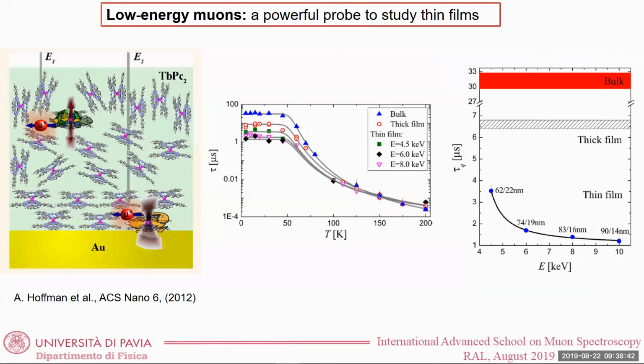Just to give you an example, this is again a molecular magnet, terbium phthalocyanine. In this study, done at LEM at PSI, we managed to learn, by studying the relaxation rate of muons implanted at different depths, in one case close to the gold substrate and in the other case far from the substrate, that the dynamics of the spins of this terbium in this organic molecule was quite different close to the surface. The dynamics was much faster, rather than, you see a turtle here. Of course, it's not present in the sample, but the dynamics here is much slower. And this is a nice application of low energy muons.